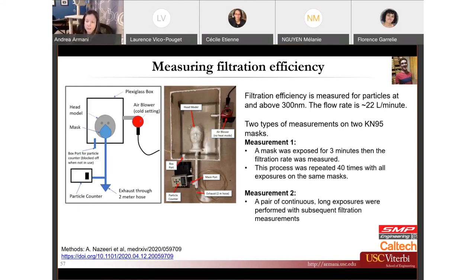We did two types of measurements on two KN95 masks. So the first measurement, and my cat's about to appear. Sorry. So the first measurement was a 3-minute exposure of the mask. And then the filtration rate was measured. And then we repeated this process 40 times on the same mask. So we basically repeatedly exposed the same mask for 3 minutes, 40 times.